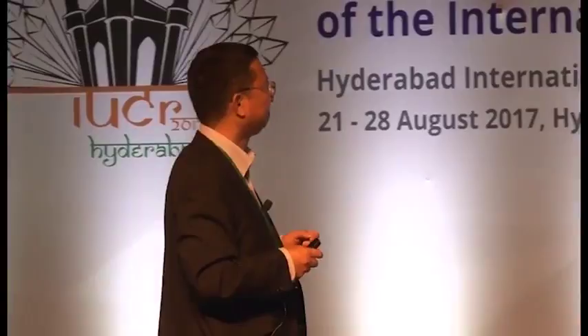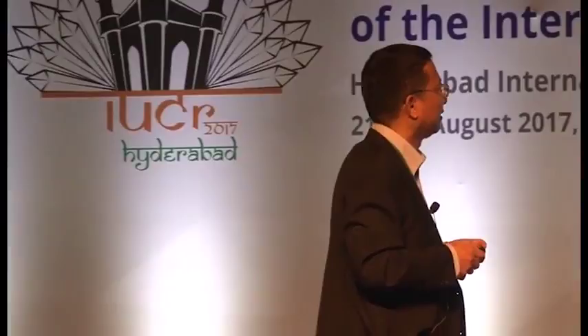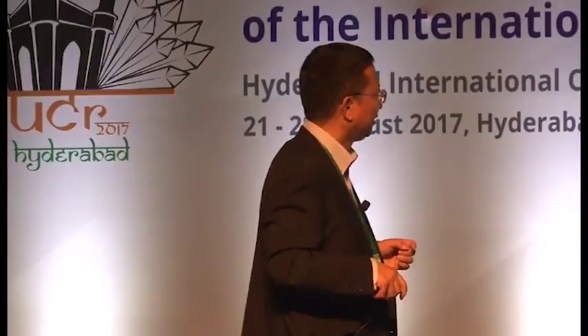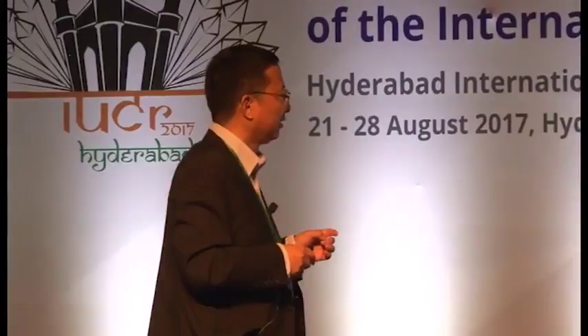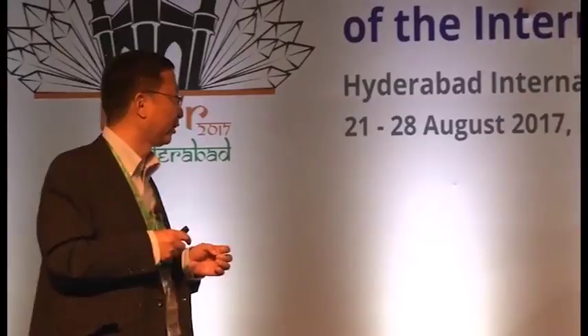What's the easy axis for the molecules? We cooperated with Sessoli and group, and using an angular resolved magnetometer combined with some ab initio calculation, we can determine the easy axis along this direction. It's perpendicular to the ligand plane. Also using torque magnetometry, we can get the same conclusion, the easy axis around this direction.